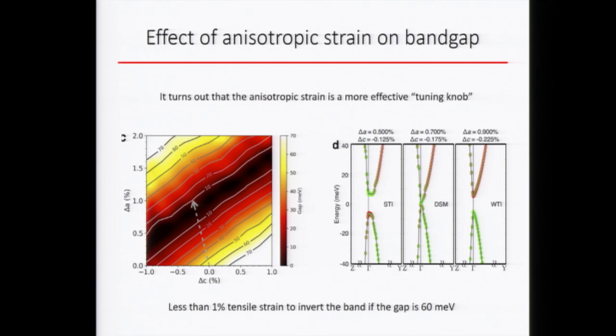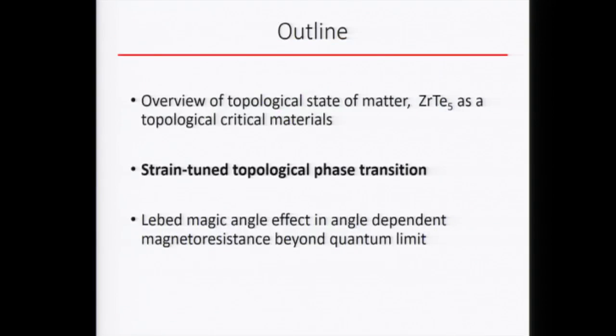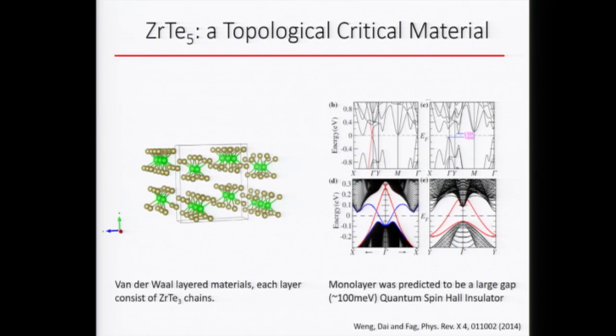Right? That's what this diagram shows. Pulling up to the left, you're pulling the layers apart, right? See, the z-axis is getting longer. No, actually, it turns out that it's not simply controlled by the z direction. The band inversion of this material is actually controlled a lot by the hopping between the chains as well. So it's increasing, with c decreasing, right? Increase and then decrease.